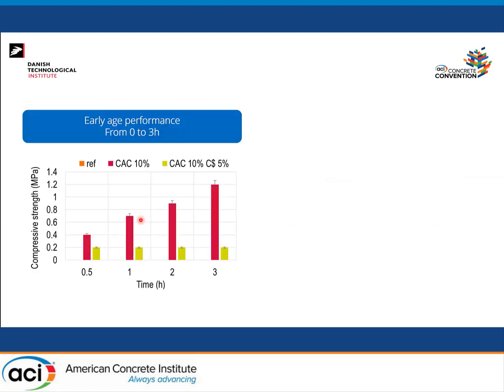So, and that's why I mentioned the compressive strength tests were very marginal in this research, but it's just to pinpoint that if we look only at early age performance, which would be the most interesting part if you're doing a print, and the print will be in the course of 30 minutes maximum, the compressive strength test results would show that my mix, which is a combination of the reference mix added with a slurry with 10% calcium aluminate cement, has a substantially higher compressive strength over the course of the first 3 hours compared to the mix that has both calcium aluminate cement and calcium sulfate, due to that flash setting effect I mentioned. So you can clearly see that already in the first half an hour, and then it continues.